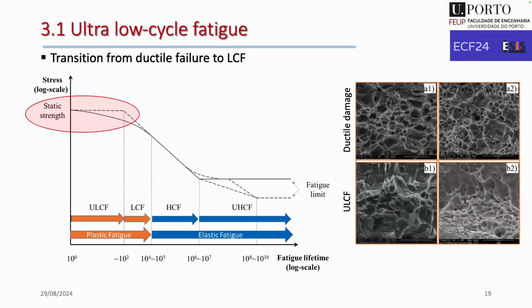And for that, we believe that we are talking not of low cycle fatigue, classically speaking, but in this fatigue regime, as you can see here on the bottom fractured surfaces, we have a mixture of crack propagation and some dimple formation, which is typical from the static ductile failure. So we believe that when we are in this region, the low cycle fatigue traditional approaches like Coffin-Manson will not work properly. This is already documented in the literature, that Coffin-Manson will overestimate the fatigue life predictions in this very short time duration.